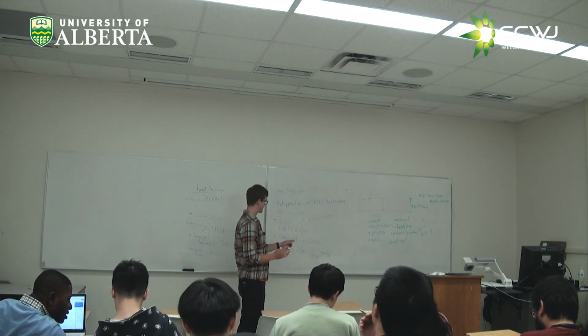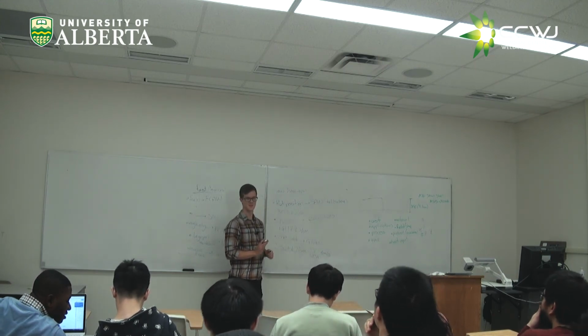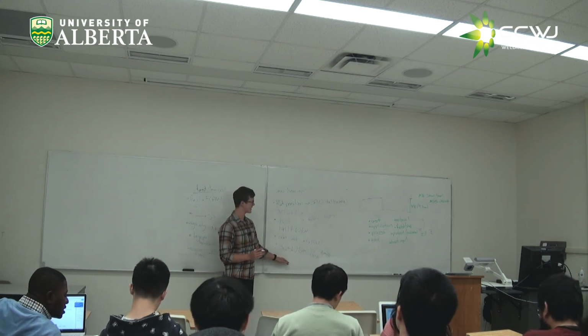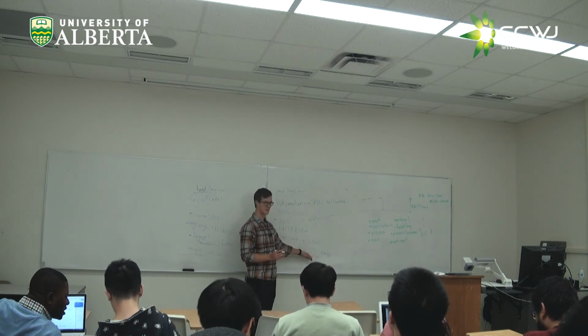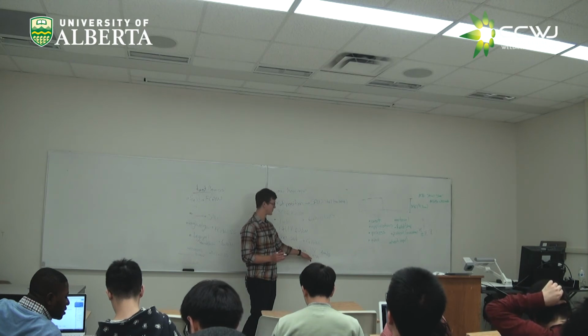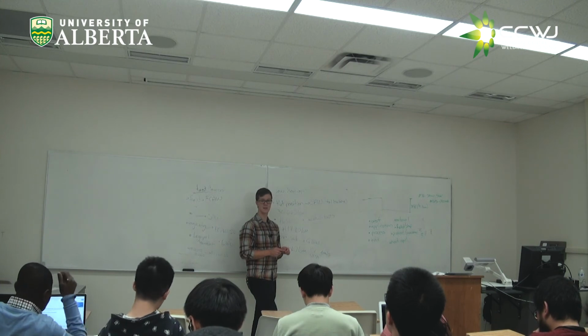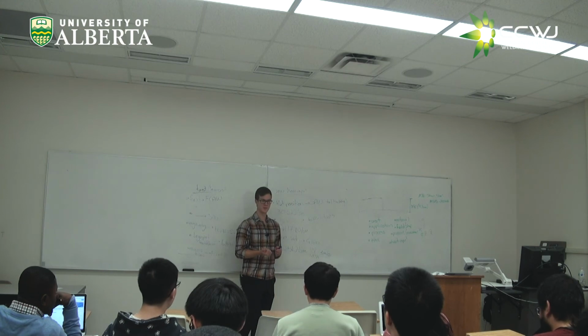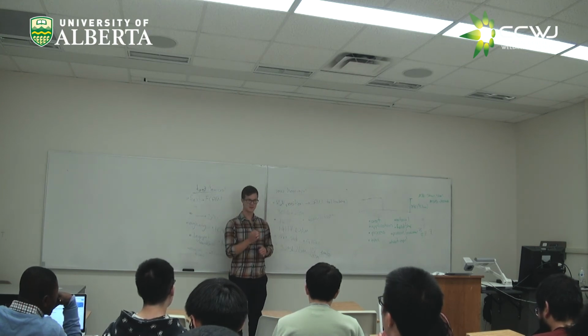Now, typically, just so you all have a chance to take a look at this, I think this calculation is something you should all be familiar with now. My guess is at 4 millimeters per second, depending on what your joint fit up was, you're going to have to do probably multiple passes with this sort of parameter. So this is pretty close to what we were doing when we did TIG welding in the demo. I think you saw it on aluminum, but we were putting down pretty small beads at about 100 amps, about 11 volts when we were using argon.